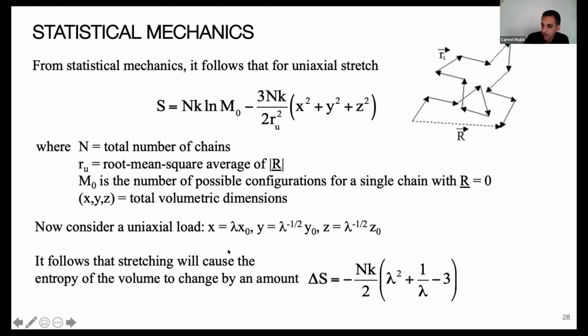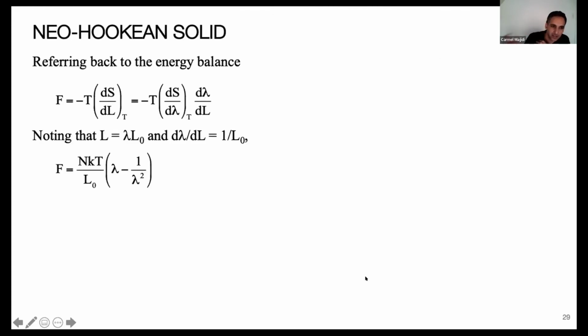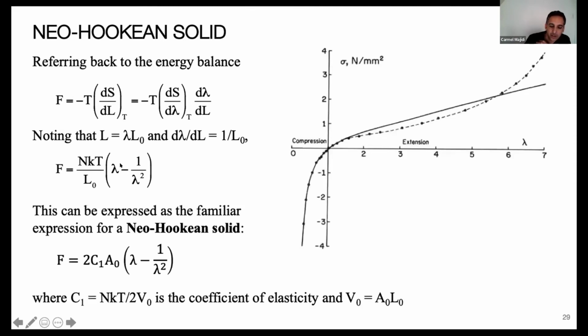And if we now take this volume and deform it, we can relate those dimensions, the X, Y, Z components of the volume, with stretch. And in the case of uniaxial loading, we stretch along the X direction, which means that we have to contract along the Y and Z. We get the corresponding change in entropy, plug this back into our energy balance, and that gives us a relationship between force and stretch that turns out to have a form that looks like our familiar expression for a neo-Hookean solid. So this is the foundations of hyperelasticity, all originating from principles of thermodynamics, and